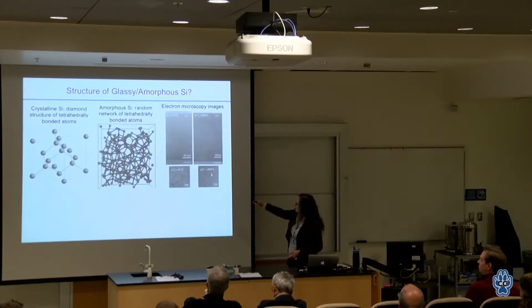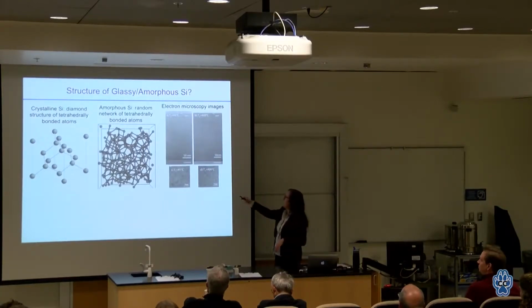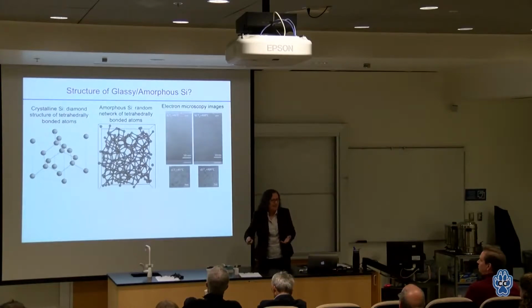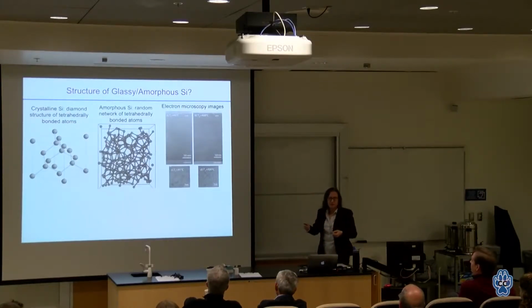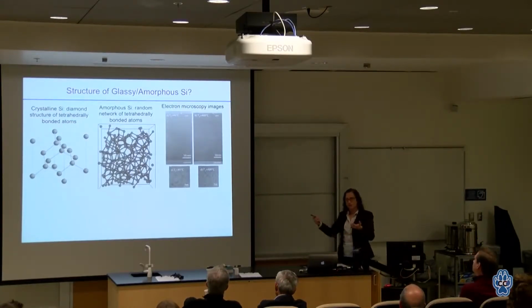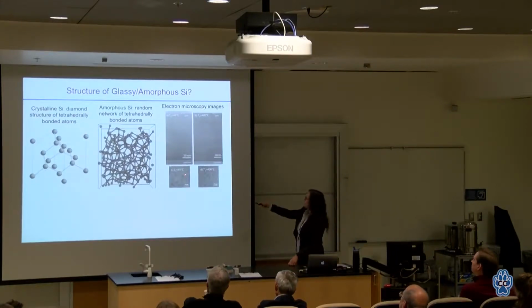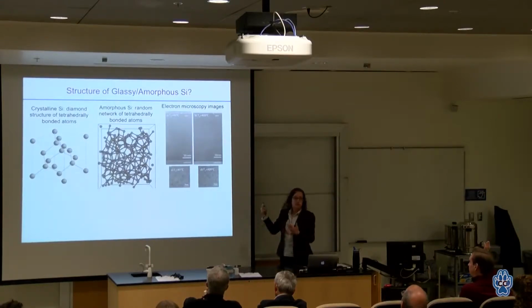If you look hard in a little bit higher resolution image, just an image on the screen, you can see little dots. It's kind of like atoms. They're not actually, rigorously, it's a Fourier transform of a Fourier transform. But the end result is there's no difference between those that you can see. This is the low resolution, bigger scale image, and again, no significant difference.